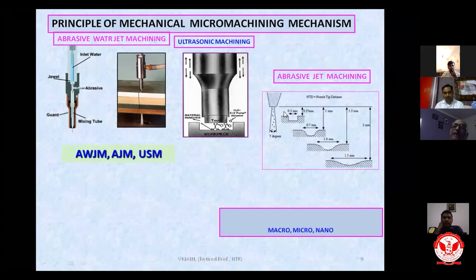And when these abrasive particles with high kinetic energy hit the workpiece surface, they are able to create a cavity of this kind. Depending upon the shape of the nozzle, you get the shape of the cavity. And the distance between the bottom face of this nozzle and the surface from where you are removing the material, say this surface over here, that distance is known as nozzle tip distance.